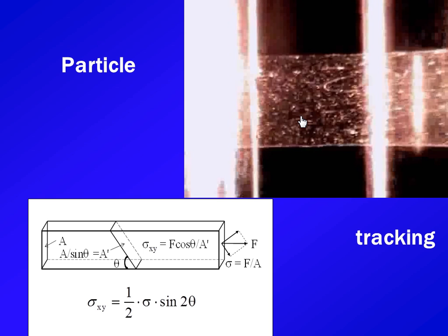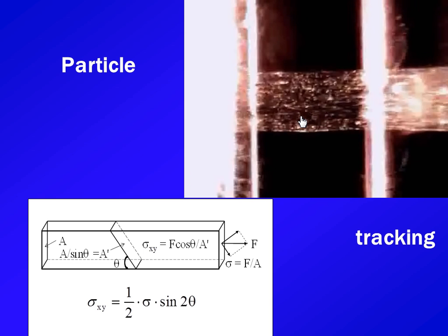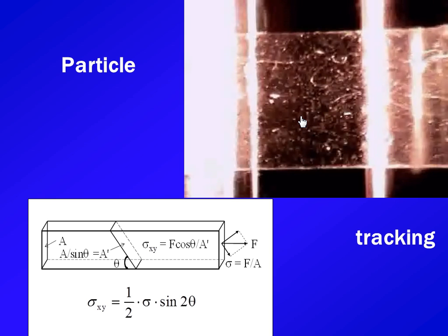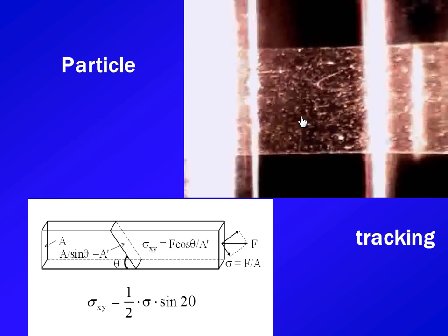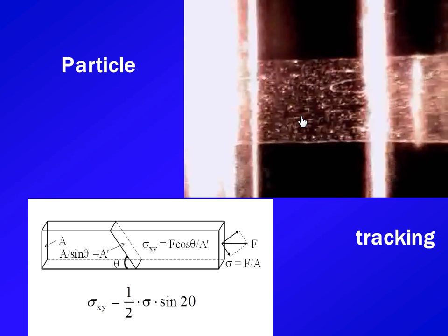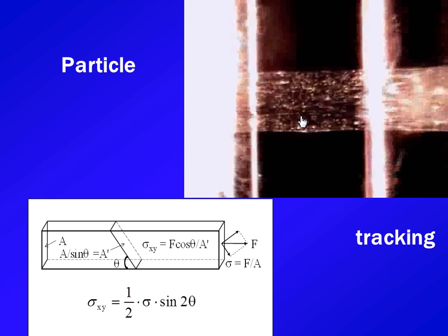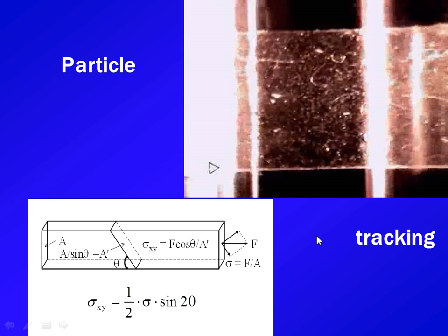And the system knows the chain, and it's very intuitive. The chain knows to slide perpendicular to the stretching direction is much more difficult than at an angle, which is by shear. So the shear yielding becomes the favored mode that leads to failure or initializes the non-uniform deformation.